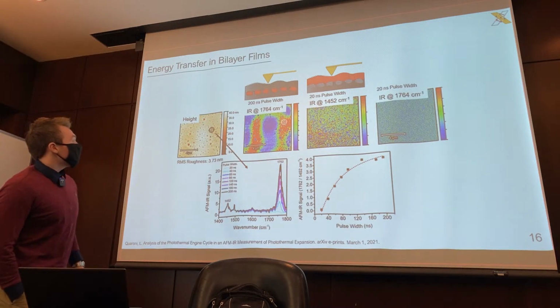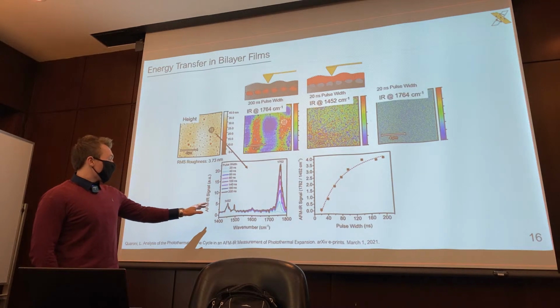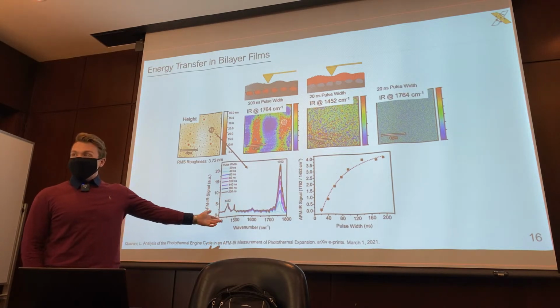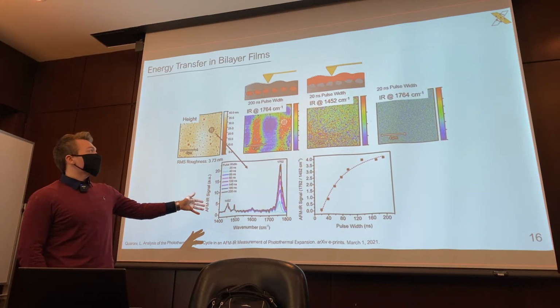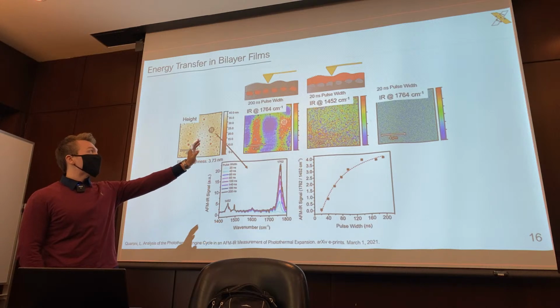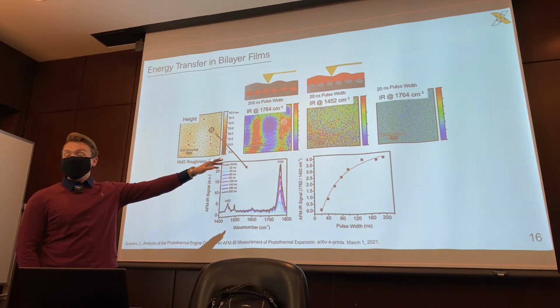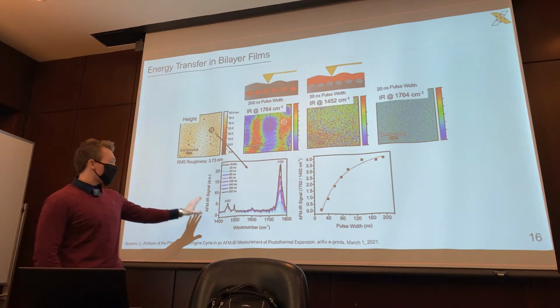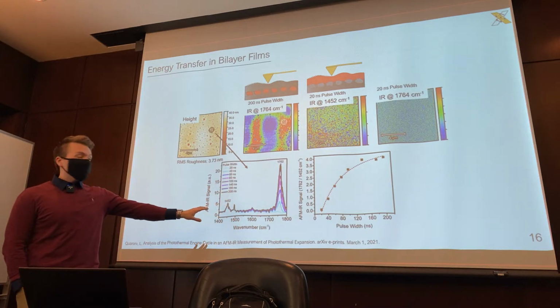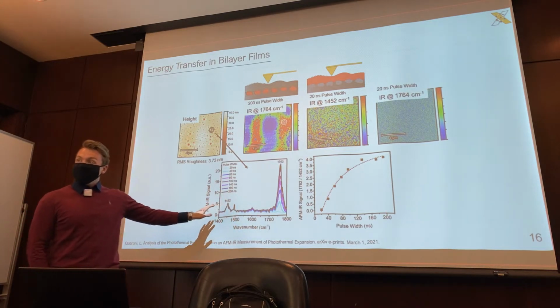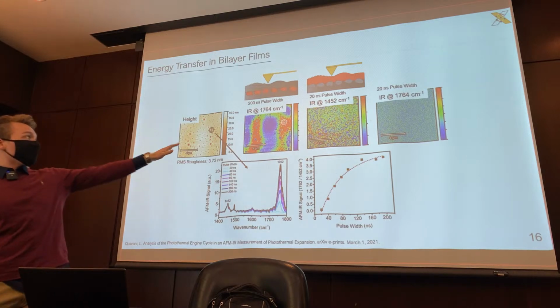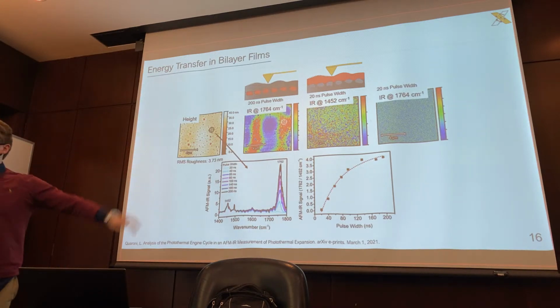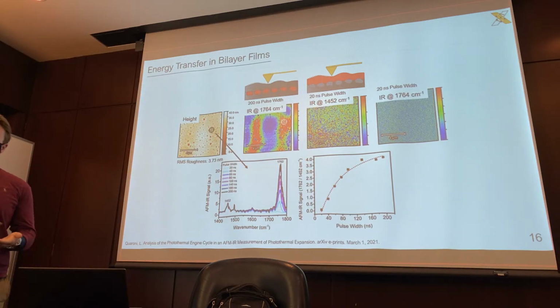If we did not treat this data at all and left it as is, we would still be able to see that same structure at 200 nanoseconds at 1452. We should see that exact same structure. It's just that this is post-treatment, so it's normalized at 1452. So that 1452 would not disappear, because if you detect it at 20 nanoseconds, you will certainly detect it with 200.